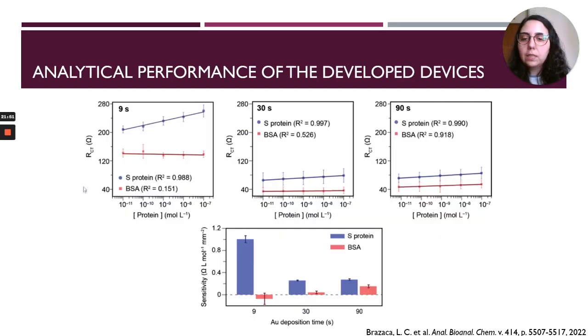Okay, we then built calibration curves using EIS measurements. So here we're assessing the charge transfer resistance of our electrode. We can see that for 9 seconds, when we use S protein, meaning our target, we do have an increase in RCT with increased protein concentration, as we expected, because the surface of the electrode is being blocked. When we use a control molecule, such as BSA, we do not have this increase. So the 9 seconds deposition time is working exactly as expected.